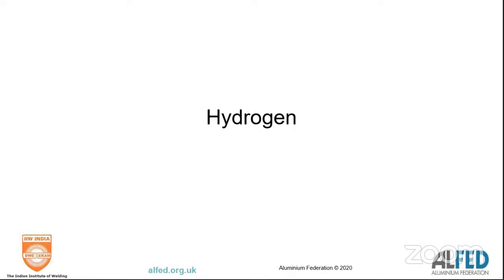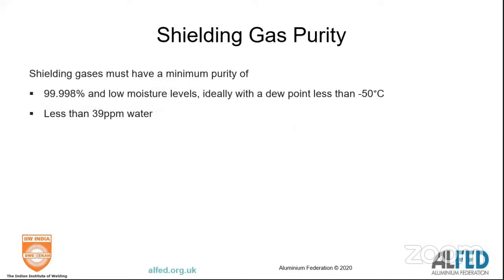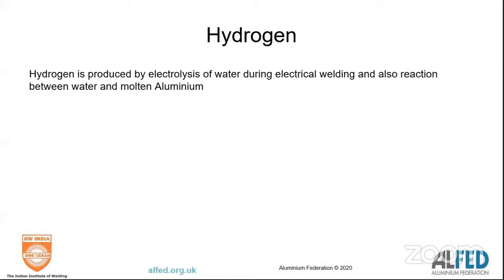Now, hydrogen is actually a problem of aluminium, but unlike steel, aluminium is not prone to hydrogen embrittlement. So that's one of the properties of aluminium. It's not prone to hydrogen embrittlement. If you're welding, you now need shielding gases, and those shielding gases have to have incredibly low moisture levels, typically a dew point of less than minus 50 degrees C, and certainly a water content of less than 39 ppm. So you're looking at very dry shielding gases.